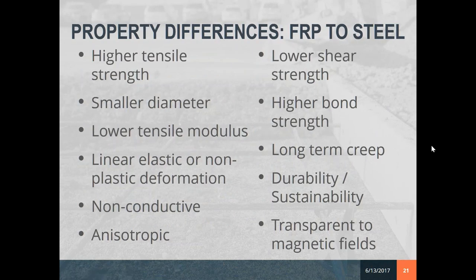As we talked about, you have a higher tensile strength, a smaller diameter, the lower modulus. FRPs have more of a linear elastic behavior. We'll show you an example, I think, later in this presentation, where steel has a plastic deformation. Once it deforms, it stays deformed. With FRPs, they'll actually rebound back and re-straighten themselves out. Again, they're non-conductive. And you could read the rest of the properties there.